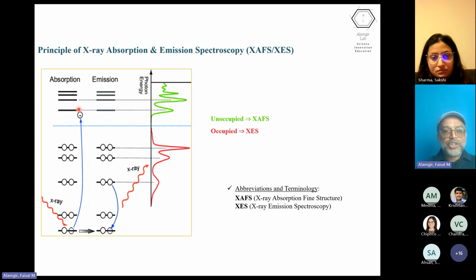If it has just enough energy to cross the Fermi level and fill one of the unoccupied states, then it is basically going to give you information about the densities of the unoccupied states, because the transition matrix, that is the probability by which this electron gets promoted to these empty states, is directly proportional to the densities of these final states. It's also proportional to other things, so one has to be wary of that. But the fact that it is proportional to the densities of the final states means that we can use this as an analytical tool to measure the chemical state of the element in question.